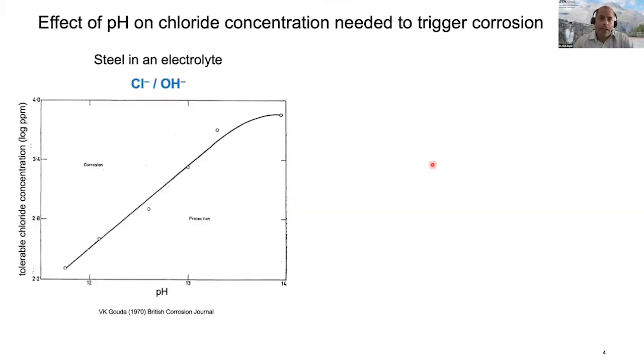So when it comes to initiation of corrosion in concrete in the presence of chlorides, it is very well known from previous studies, such as the famous work by Hausmann, who revealed a critical chloride hydroxyl ion ratio, or the work from other important researchers in the 70s, that we have this ratio, chloride to hydroxyl ions, which is important for the tolerable amount of chlorides in the solution before we get corrosion. So we can see here in this log-log plot that we can tolerate more chlorides when we have a higher pH. And we were wondering if this concept, which is valid for steel in electrolytes, steel in solutions, is also applicable to steel in concrete.